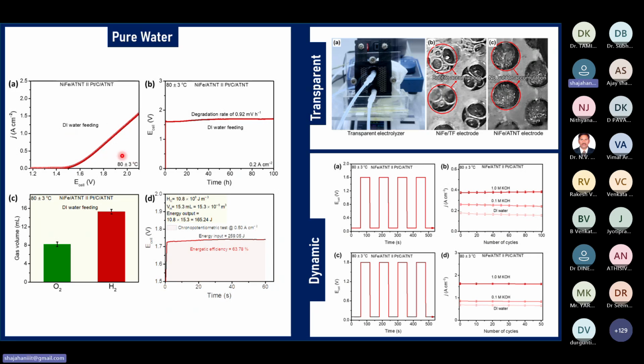So with pure water, we also successfully reached almost 1 ampere per centimeter square, with stability of 100 hours with the pure water. So it is also good. And gas efficiency with the pure water itself, we got 63.78%. It's actually good. With only nickel Fe, we got 63.78% gas efficiency. This is also very good.